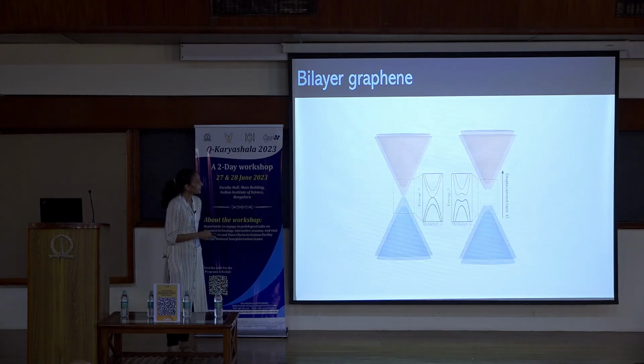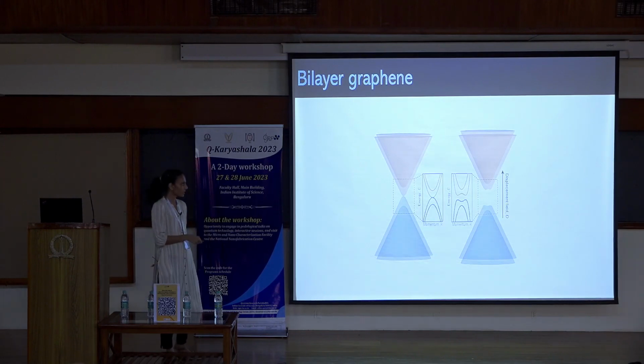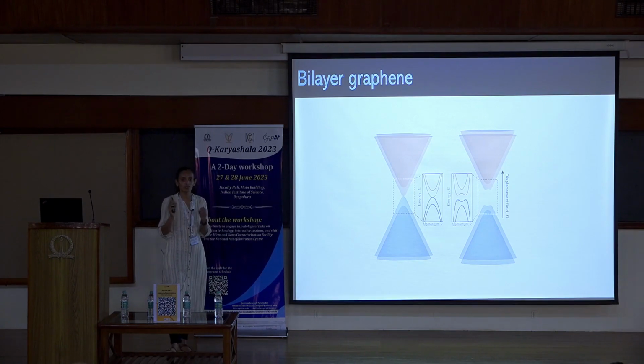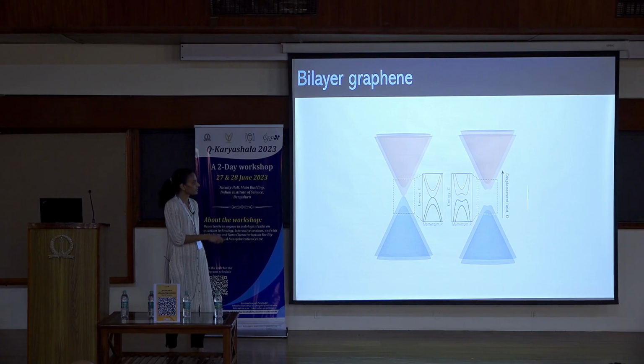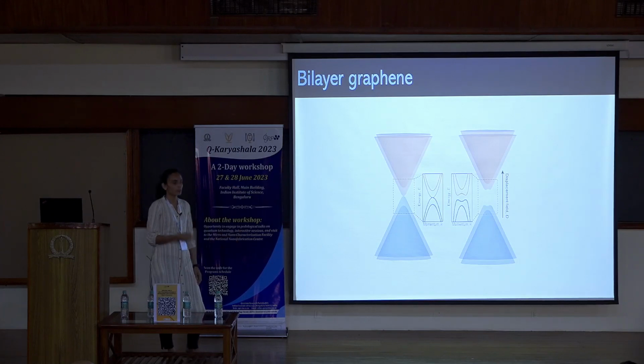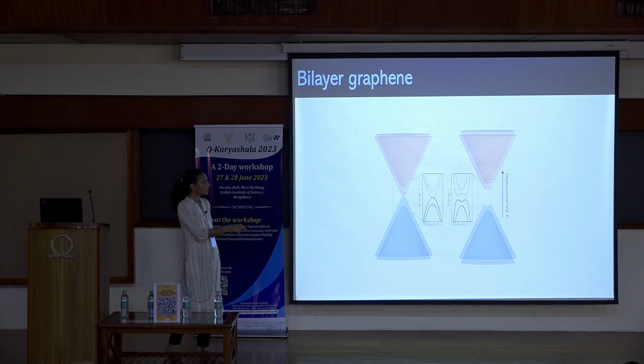Okay. Now bilayer graphene is also interesting because in bilayer graphene, if you take a bilayer graphene and you put an electric field in a perpendicular direction, what happens is it opens up a band gap. Now band gaps are important because if you're talking about creating a device out of this, you want the device to turn off, which means you need to have a band gap. So this was an important discovery, that putting in a displacement field or an electric field in the perpendicular direction opens up a band gap in bilayer graphene. In single layer graphene, you don't have that. So many of the electronic devices that you may read about, even for quantum computing purposes, use a bilayer graphene.